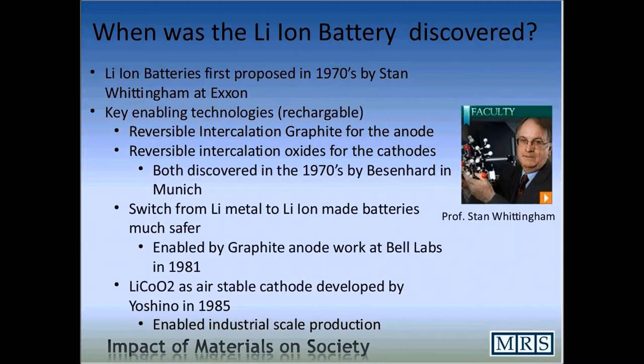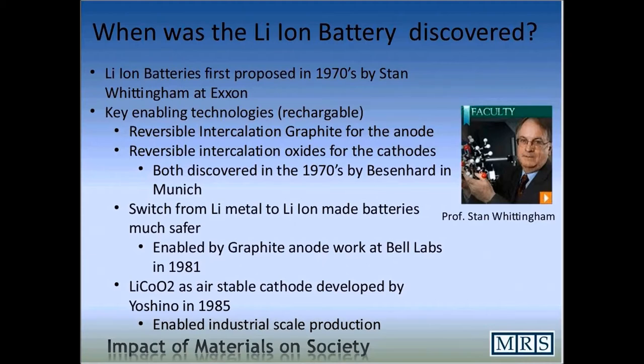The switch from lithium metal to lithium ion made the batteries much safer. The original concept was to use metallic lithium as the anode; however, that is a very reactive metal. By using lithium stored inside graphite instead, you create what's called a lithium-ion battery, which is much safer. Finally, coming up with a stable cathode in air was critical because you needed to enable industrial-scale production without everything having to be done in a glove box. That was enabled by the discovery of lithium cobalt oxide in 1985.